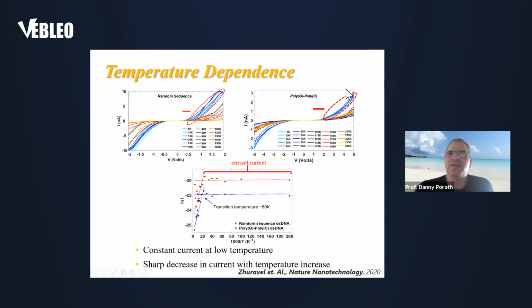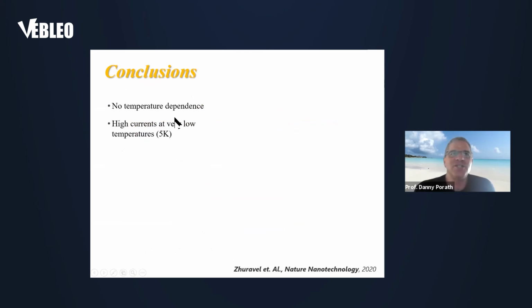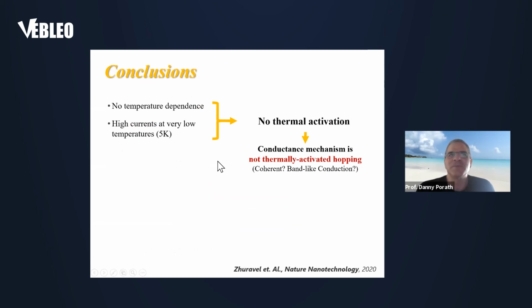And if we look at a vertical cut of the current versus the temperature, here in this Arrhenius plot, we present the log of the current versus 1 over the temperature. And we can see indeed that the current is not changing much up to 50 degrees, and then there is a slow reduction of the current. So to conclude the experimental observations, there was no temperature dependence up to 50K, and there were high currents at the low temperatures, and that means there's no thermal activation. It cannot be thermally activated hopping.